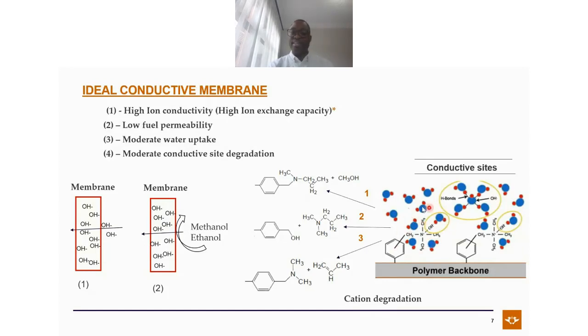This is the design of a membrane. So you have your polymer backbone membrane and you have a conductive site. You see there's an aromatic structure, then you have a nitrogen-based conductive site. If you put this in OH solution, chemistry tells you that this will degrade via Hofmann elimination or SN1 reaction or E1 reaction, which is chemistry that we studied in our undergraduate. And correctly so, that will happen. But we want a polymer backbone with a conductive site which will prevent that. If it does happen, it happens at a lower rate.